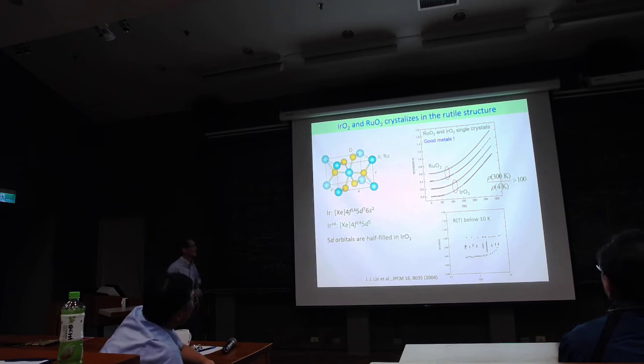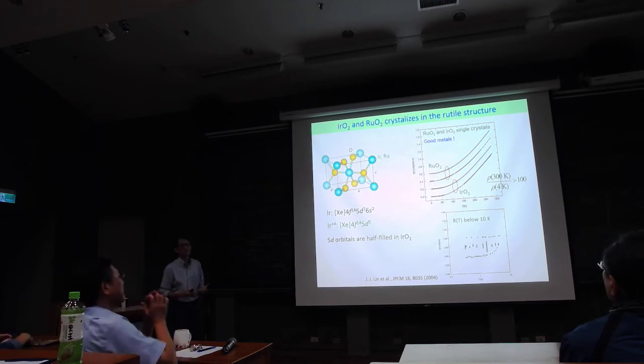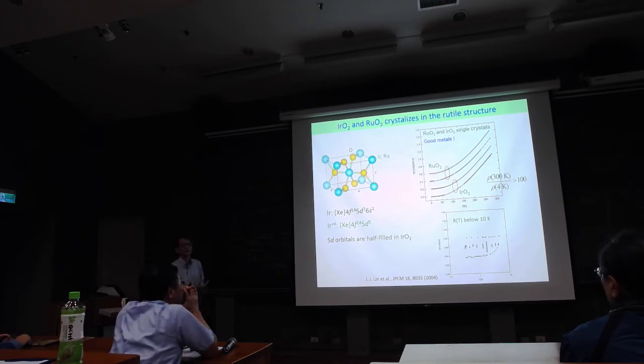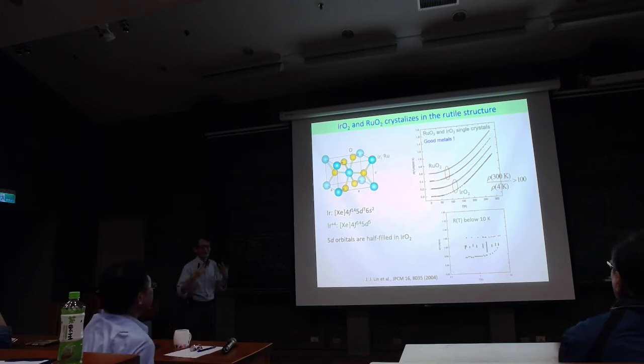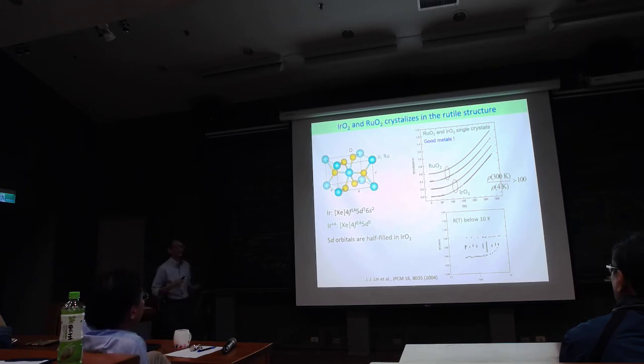What I want to say is that if you have very good crystals, no oxygen vacancies, no defects, these are good metals. And if you go to very low temperature, below 10 Kelvin, you can see that resistivity goes to a constant, residual resistivity. So this is caused by electron scattering with some elastic or static defects. And then if we take our oxygen out, we will see orbital Kondo effect, two channel and one channel. That's what I want to show.